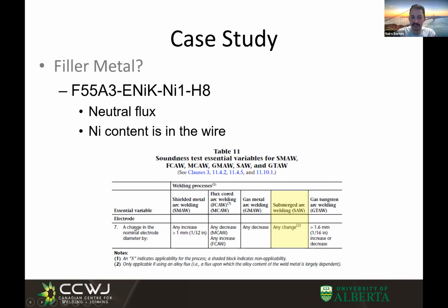But more importantly, if we look at the essential variable table for W47.1, what we'll see is that with submerged arc, if we'd like to use any other size of electrode diameter other than the one used for the test, and we use an active flux, we can no longer change that wire size freely. But if you use a neutral flux, you can now change that size of wire freely without having to redo the testing, which is an awesome thing. So essentially, if I test it with a 3.2 millimeter wire, and then 2 months later I do a project where I want to use a 4 millimeter wire, I can make that change without having to requalify my procedure. Where if I used an active flux, I would have to redo the entire qualification. So it's again that idea of future proofing by being familiar with the code.